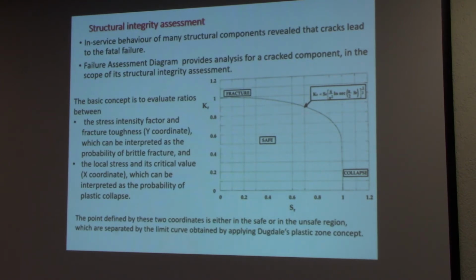And by saying that in a descriptive way, let us also assume that there is a simple proportion. If the point is here, it is, let's say, about 5% to the limit load, so the probability is 0.95. If it is just here, maybe it is 0.05. I do admit it is arbitrary, but trust me, it works. So we use it, and we don't much excuse it. And of course, by doing so, we always do it in the conservative way.